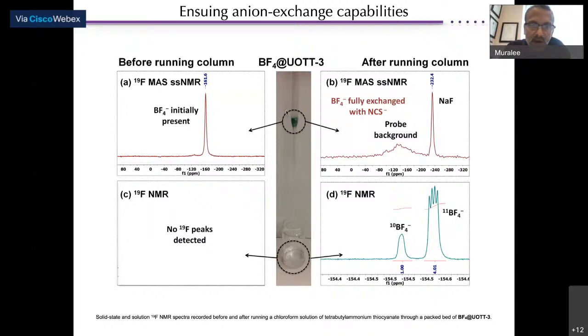Here is the solid state NMR of this ArMOF, showing that BF4 is present. Then after, in the solution at the bottom, of course, we don't have any fluorine NMR detected initially. But the moment we started flushing through with a chloroform solution containing tetrabutylammonium thiocyanate, the thiocyanate is now exchanging with the BF4 minus, and then you can probe the BF4 minus here, and no BF4 anions are detected in the leftover afterwards. So it's pretty much almost 100% exchange with this anion exchange.